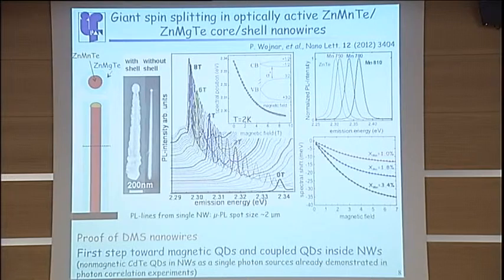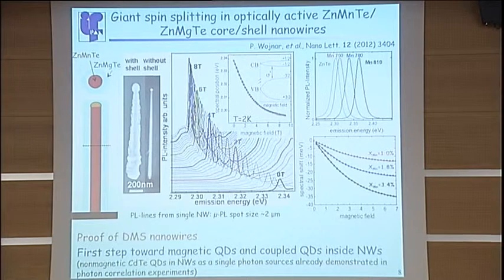So this is just a nanowire made of zinc manganese telluride with a shell to make those nanowires optically active, and you study the microphotoluminescence from the single nanowire, and you can clearly see the gigantic spin splitting, which is the very typical characteristic of diluted magnetic semiconductors, and the spin splitting scales with the concentration of manganese in the sample. So this is definitely proof of diluted magnetic semiconductor nanowires. We consider this a first step toward producing magnetic quantum dots and coupled quantum dots inside the nanowires. We have already shown that it is possible to produce cadmium telluride quantum dots by correlated spectroscopy.